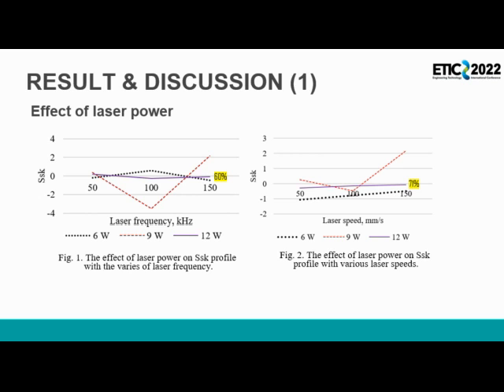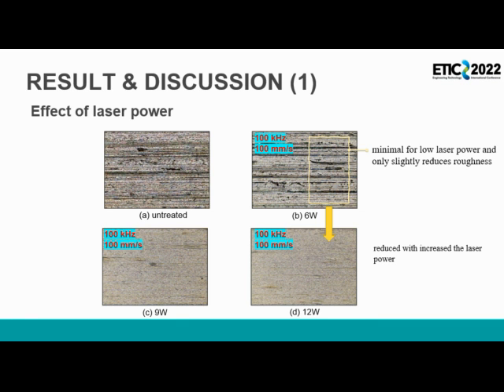Figure 1 shows that the laser power of 12 watt will generate a skewness that is consistent and getting closer to zero. There is a 60% increase of skewness with the laser power of 12 watt and laser frequency of 150 kHz, while figure 2 shows an improvement of up to 71% of skewness for the laser speed from 50 to 150 mm per second. The figure above demonstrates an improvement in both the quality and smoothness of the surface profile.